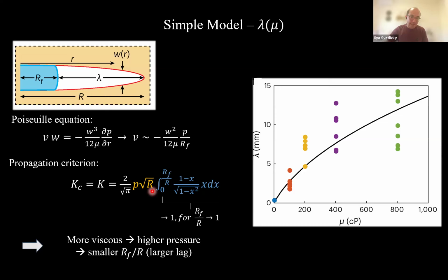So you might need to repeat the analysis if you now have a 1 kilometer crack, say, or something like that. I think the framework is the same, but the numbers will differ. And regarding the compressibility, the quick check that we did between the difference in compressibility between pure water and pure glycerol, or some mixture of the two, didn't make any difference to our result. And the third point, which is extremely important, is of course that we are focusing on several jumps of the crack, meaning that the assumption is that the pressure doesn't drop significantly in these intermediate events. If you wait very long, of course, the pressure will almost reach zero. So we are focusing somewhere in between, just because we don't know how to calculate the pressure. So we need to assume it's constant between events.